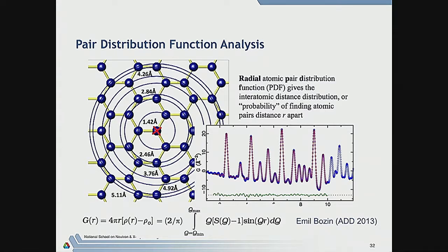Although you can see that it would be particularly sensitive to, for instance, deviations at very low distance. It becomes rather difficult to use it to see deviations from the average structure at very large distance because there are so many atoms that are in the average structure that seeing deviations from that can be quite difficult. So it's a technique that tends to be better at small r. I don't know if there are any PDF specialists that would disagree with me. But anyway, that's our claim. So this is the standard PDF.